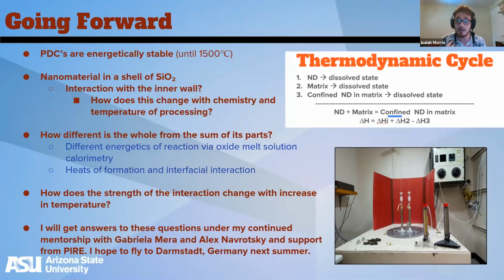And I am looking to measure the different energetics of reaction via oxide melt solution calorimetry and utilizing this thermodynamic cycle that you can see here on the right of first, dissolving the nanodiamond and then dissolving the matrix and then the confined nanodiamond in the matrix. And from there, measuring the different heats of solutions to find the heats of formation and what actually are the thermodynamic properties of that interfacial interaction between the nanomaterial and the shell and the silica shell itself. And how does the strength of this interaction change as you increase in temperature, as you change this nanomaterial? Will the interaction change?